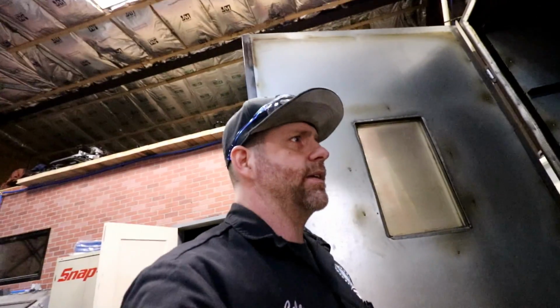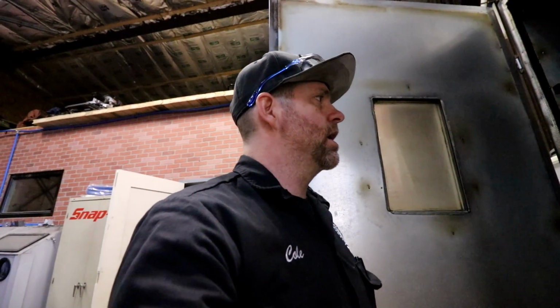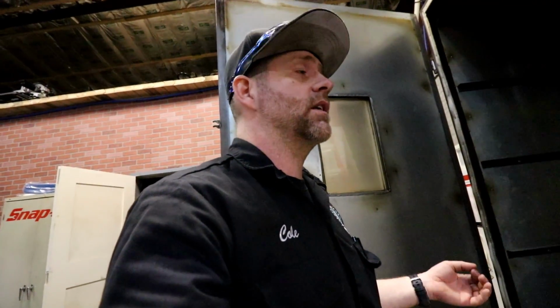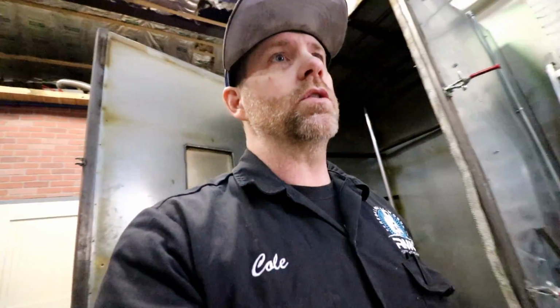All right, over here you can see in the oven, this is how I hung three pieces in here and annealed them that way. And typically when you powder coat, you're going to be at about 400 degrees generally to flow out. So just in the future, if you are powder coating 6061 and it's heat treated, you are going to anneal it. You're going to lose probably at least half the hardening, maybe more.